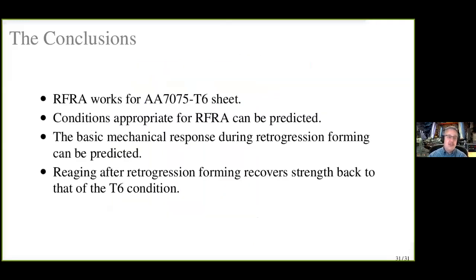So what are the conclusions? Well, we believe we've shown that this retrogression forming and reaging concept works quite well for 7075 T6 sheet. We think it will work for some other alloys. I mentioned the 6013 alloy. We can get some benefit from using it for that alloy, and there are other alloys that may be applicable to, but we've really just thoroughly investigated 7075.